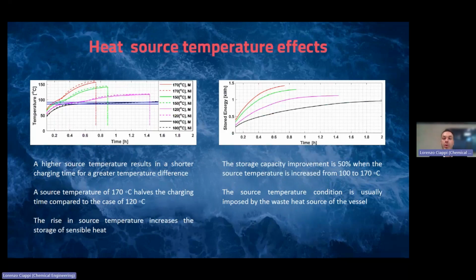A sensitivity analysis was conducted to evaluate the effects of design parameters and application parameters. In particular, the temperature of the heat source is linked to the available waste heat on board, so it's a boundary of the application case. And we can see that the increase in temperature of the heat source has a strong effect on the duration of the charging phase of the system and on the energy that is stored by the PCM.